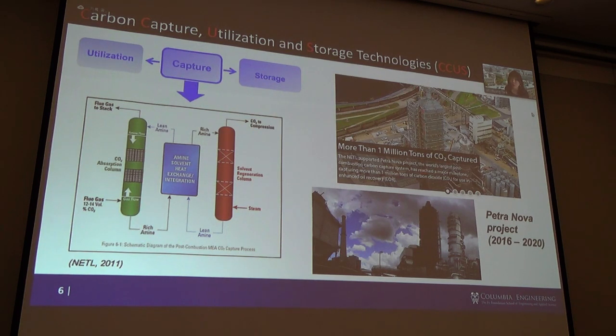One of the reasons we always knew the processing energy consumption would be very high is because of the concentration of amine we can put into these liquid solvents. Generally, these amine solvents can be used at maybe up to 30%, which means that 70 to 85% of the liquid solvent is in fact water. And because water has a high heat capacity, heating up all the liquid solvent and cooling it down very fast and then doing repeatable cycles always requires large energy consumption.